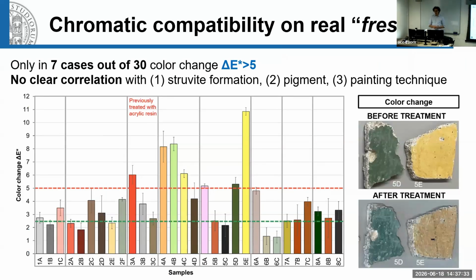In addition to laboratory mock-ups, we also performed a study on real frescoes coming from some monuments in Italy. And in general, we found good results on samples with different colors. Only in a few cases, the color change was actually not acceptable. So you see here, in this specific case, the initial sample had a very bright yellow color, which becomes, let's say, darker and not so pleasant after treatment. So in that case, it wouldn't be acceptable to use this kind of treatment.